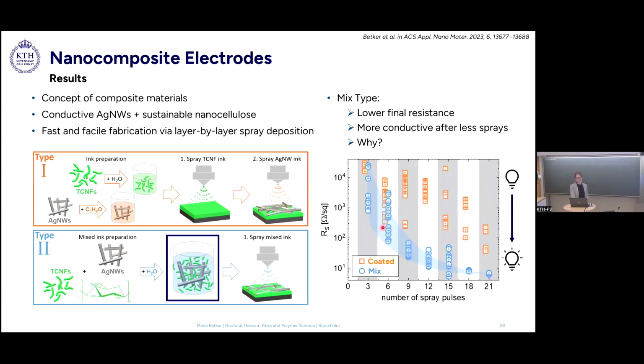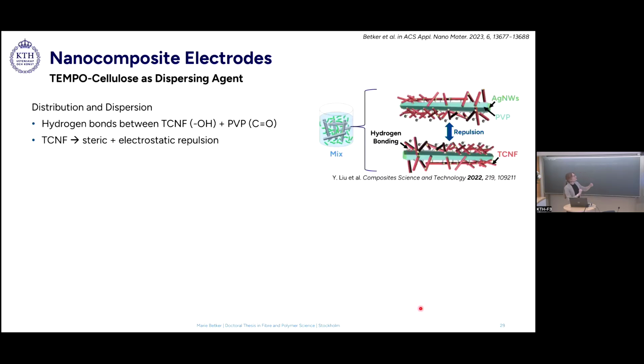So you can directly see, if you compare blue and orange, that the blue electrode performs much better because it has a lower final resistance, and it also becomes more conductive after fewer sprays. And I want to look into the details of why that actually is. So, yeah, the contrast is a bit low, but I hope you can see it. So in the right corner, you see an image of what is going on in the mixed ink on the nanoscale.